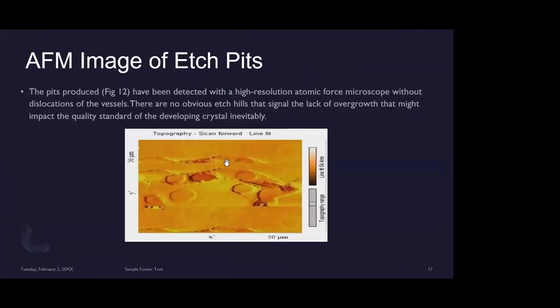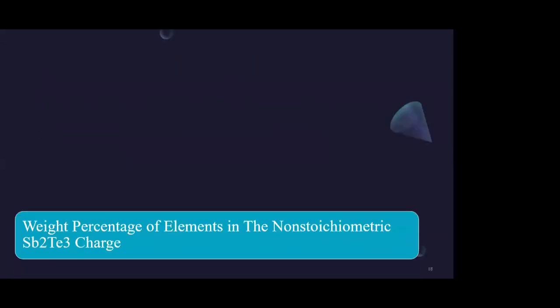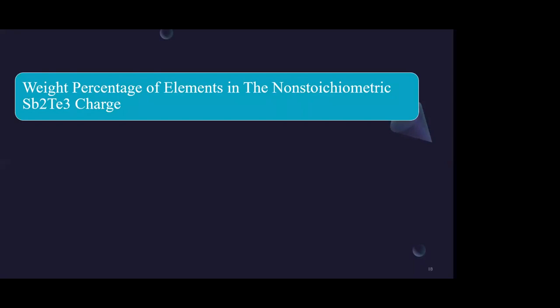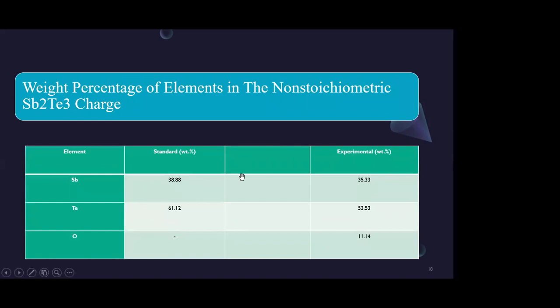And the AFM image of etch pits was also analyzed. The pits produced have been detected with a high resolution atomic force microscope without dislocations. There are no obvious etch hills that signal the lack of overgrowth that might impact the quality standard of the developing crystal. Weight percentage of elements in the non-stoichiometric Sb2Te3 charge: when compared with the standard weight percentage, the experimental one was slightly deviating, but still the oxygen content was there.